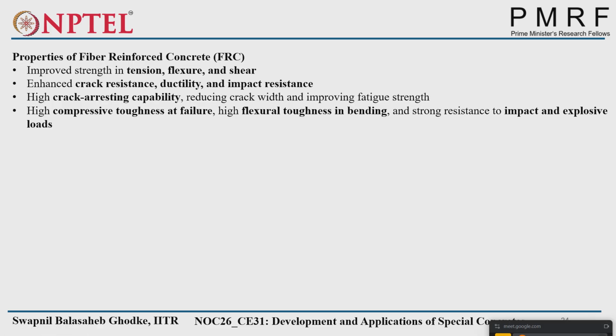So we saw toughness index, we saw all the fiber reinforced properties, types of fibers. What we get from here: fiber reinforced concrete improves strength in tension, flexure and shear, enhances crack resistance, resists crack widening, improves ductility, impact resistance, high crack arresting capability. That's why post peak or post crack behavior is more important. Reducing crack width, increasing fatigue strength, compressive toughness at failure, high flexural toughness in bending, and strong resistance to impact and explosive loads, particularly in military operations structures.